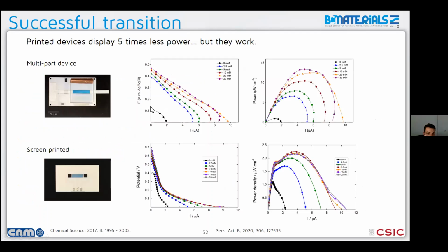So next we wanted to screen print the whole thing. So we went and replicated the same design, same geometry as we had at the beginning. And what we found was that the system was slower, which was not really a surprise, because this, at the end of the day, was about 10 micron thick when the electrodeposited Prussian blue layer was roughly 100 nanometers.